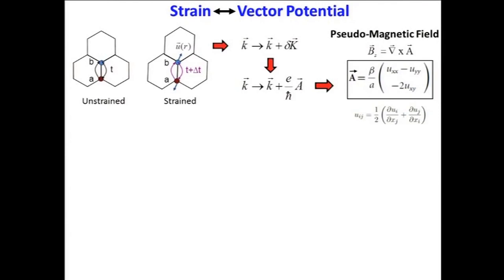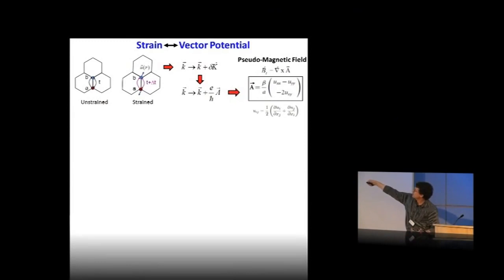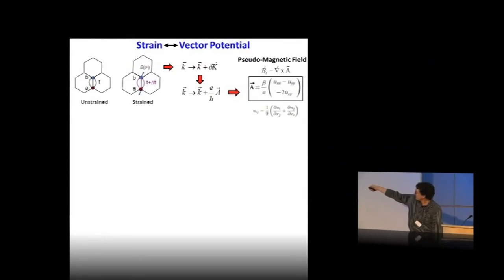Now, if you remember some basic quantum mechanics, then you might remember that if a charged particle is moving through space and you turn on a magnetic field, then what that does is it changes the momentum of the particle by an amount that's proportional to the vector potential. So take a look at these two equations, and you can see that they're very similar. And so what we can do is create a mapping between this change in momentum and this vector potential. And if you work through the details, as smart people have done, then you find that for a particular strain tensor in graphene, that will lead to a pseudo vector potential that you can write down as I've done here in this formula.